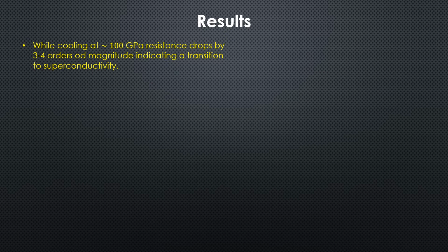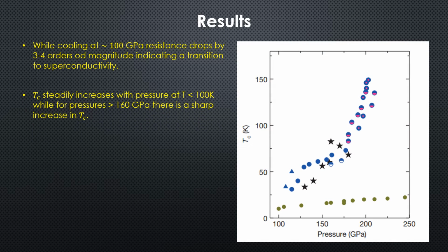Now about the results: when cooled at about 100 gigapascal pressure, the resistance drops by 3 to 4 orders of magnitude. That indicated a transition to superconductivity. It was observed that Tc steadily increases with pressure at temperatures below 100 Kelvin, while for pressures above 160 gigapascals there is a sharp increase in Tc.